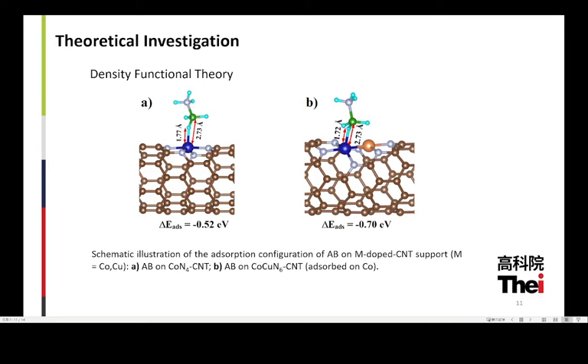Therefore, we use the cobalt-copper dual atom, and these two figures show it enhances the stability of the absorption state of ammonia borane onto the cobalt single atom site when compared with pure cobalt single atom site. Also, the cobalt-copper dual atom synergy is a promising approach to enhance the substrate absorption ability.